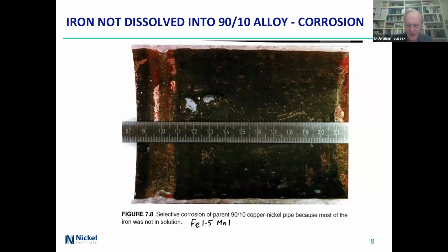This is a piece of 90-10 copper nickel pipe, which had perforated. Well, actually, it hadn't perforated - you can see on the left there the actual band where it's connected up, but it's certainly corroded. Probably, basically, this is what the report said: the iron was not in solution. It actually came out in individual precipitates and rather mucked up the actual protective action. So that's what can go wrong if you manage to contaminate the copper nickel substrate with the wrong sort of metallurgy.